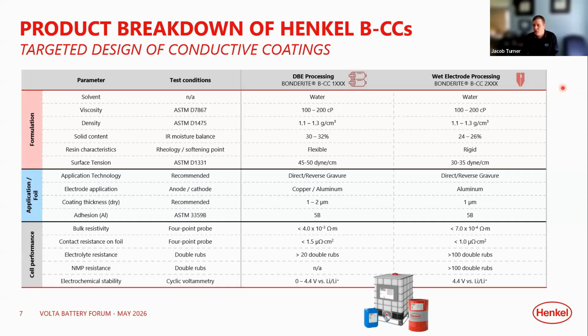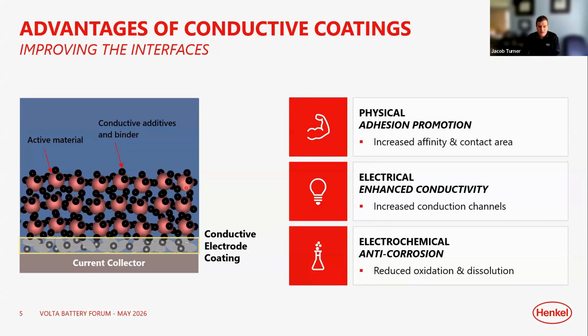I can't share the specifics, but I'll certainly elaborate on what those conductive materials are. We certainly use conductive carbon materials. There are use cases and advantages to using some of the more nanomaterials, whether that be carbon nanotubes, graphene, or your more traditional graphites, carbon blacks, and so forth. But in the end, maybe I'll just back up a couple slides. In the end, we want to form a highly conductive network both within this material and also through it, right? Because we're trying to funnel the electron transport from active materials to current collectors. So we need good conductivity in the X, Y, and Z directions. There are certainly strategies to doing that, making use of all of those carbon materials that we have available to us, to form the best network possible. Great. Thank you.